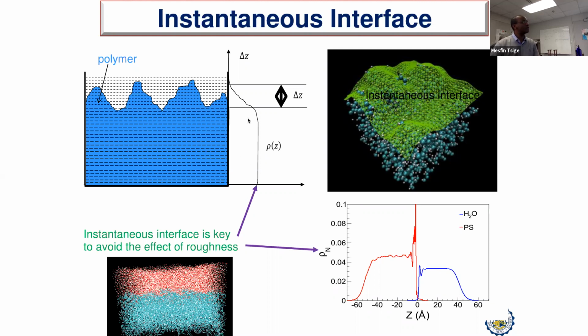The usual approach is we tend to use a slab approach, which means you take a slab, you count how many atoms you have, divided by the volume. That gives us a density. Let's say if this is my polymer, when I look in that direction, I have a constant density. And when I reach the surface part, there is a decrease in the density, more like tan hyperbolic. This is what's common in polymeric systems.